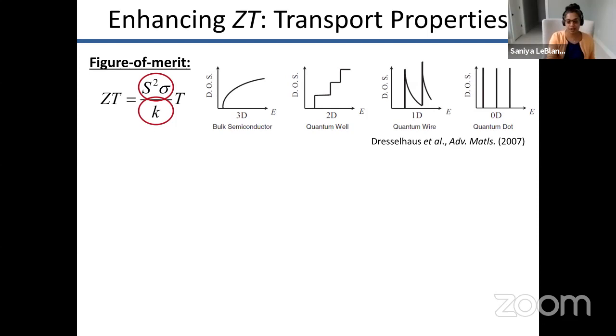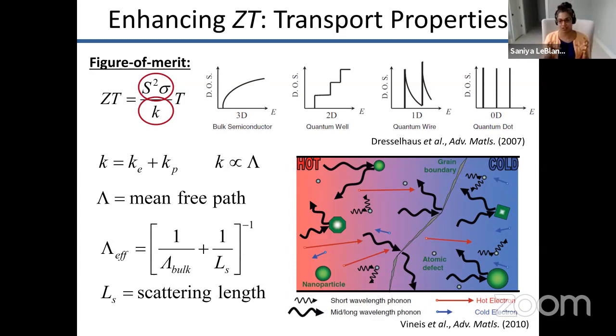So working on nanostructuring the material can increase the numerator of this figure of merit that tells us how good thermoelectrics are. But we could also think about decreasing the denominator. So how do we reduce the thermal conductivity? And that can actually also be done through nanostructuring the material. And so the way we do that is by changing what's called the mean free path of the carriers that carry heat through the material. For folks who are unfamiliar with this, I'm just going to summarize what we do here and try to make it understandable. We have these vibrations of the atoms in the material that actually carry heat through the material. And those are called phonons, these lattice vibrations.